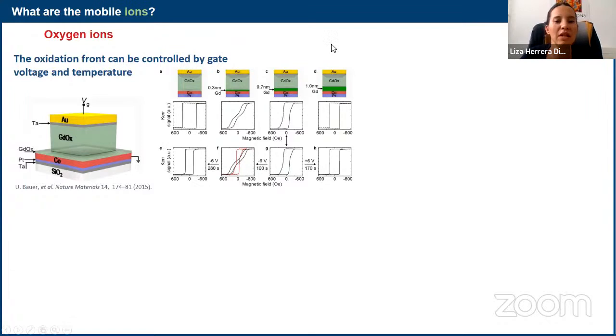So then that should be similar to what should happen with a gate, if that is really the case. And then they looked at what it does to the magnetic properties. And then they picked one, which is the 0.7, and then they applied the voltage to make this layer thicker or thinner. And they really retrieved what they had in the grown samples with thicker or thinner gadolinium. So this was really showing that this oxidation, an oxidation front in the gadolinium oxide, could be controlled by voltage, and also they were using temperature to help this process.